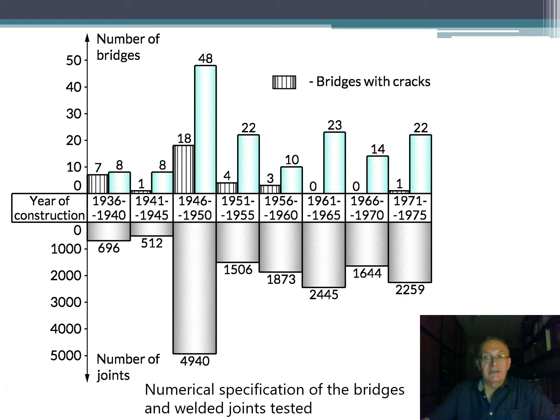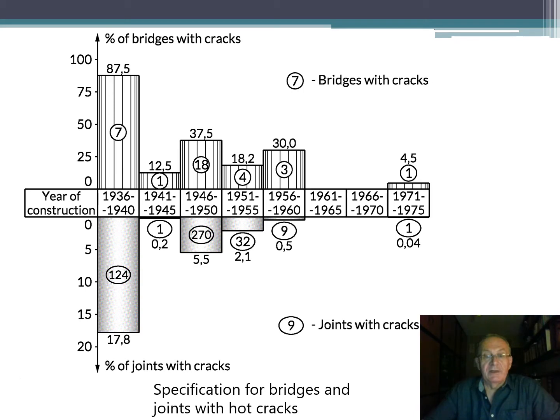Looking at further periods, it appears that the quality of welds improved, and from the 1960s, cracks in welds were only found occasionally. The second diagram is showing the bridges and joints with cracks, with hot cracks, technological cracks. For the first period from 1936, 7 bridges were found with cracks, so this is over 87% of the total number of bridges, because 8 bridges were tested from that period. The number of joints with cracks was 124, so it is nearly 18% of the total number of welded joints which were tested.